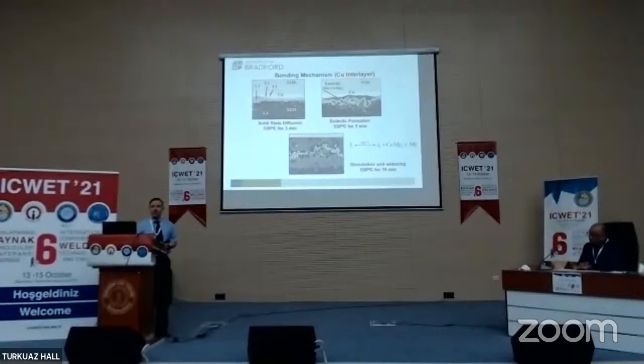So when we are working with dissimilar materials, we have lots of challenges, and the differences in both mechanical and physical properties are those challenges. So this is an example of those types of challenges. Here we see that we are joining using a copper interlayer, pure copper, and at the top we have an austenitic stainless, and at the bottom we have a magnesium alloy. So when you are looking at the bonding of different materials, we can expect interesting results.